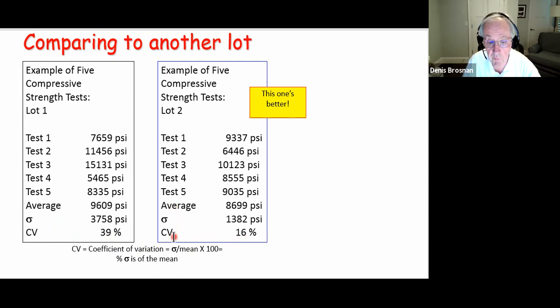So now we have 3 parameters that are talking to us about our strength value and how good it is and what it means. And actually, lot number 2 is the better lot. It has less variation in the test numbers, even though the average strength was a little bit lower. And that's something that you can see time and again in fabricating a ceramic. Now, understand that your goals are set by smart people, including yourself, that tell you a lot about what the ceramic should be. But nevertheless, you need to be always aware of variation in test values.